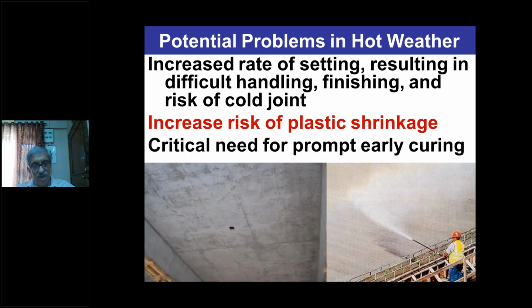And now I can show you that the soffit of the slab is crack free. This was demonstrated at one of the sites in Gujarat where the client objected that the cement supply was with cracks, etc. And to his surprise, when we put the plastic sheet and cured the concrete properly, there were no cracks visible, no through cracks, even after ponding water on the top surface.